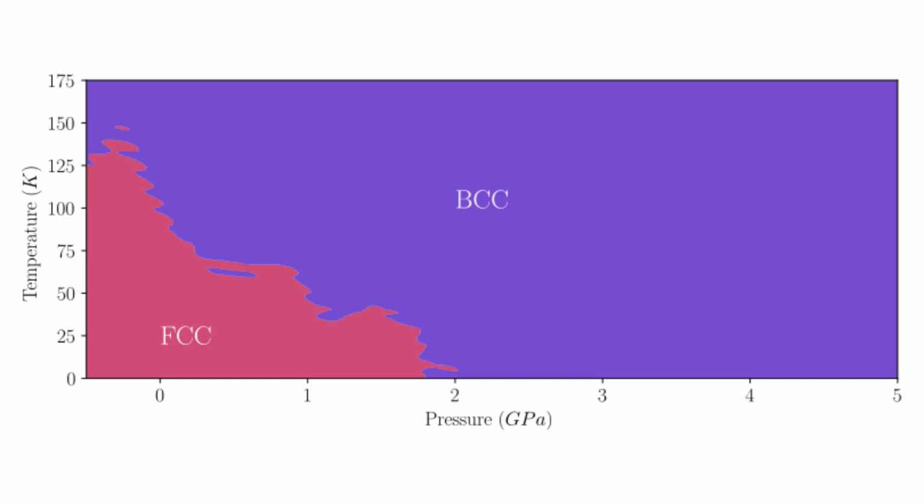Yes, actually. Here's one I made earlier. Looking at the metal sodium with FCC and BCC structures going all the way down to absolute zero. This diagram actually gives evidence against the previously held belief that sodium exists in some complicated structure called 9R at zero pressure and temperature, and instead it just likes to be in the simple FCC structure.